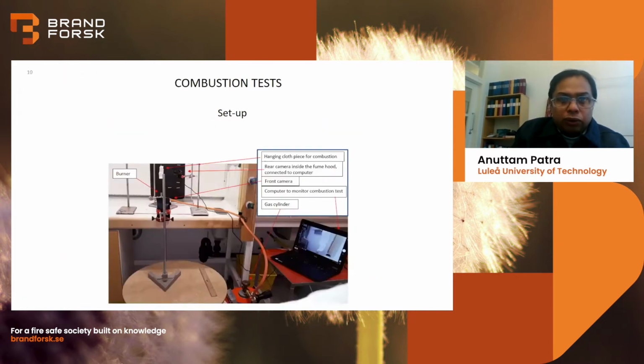Now I move to the simple combustion test setup that we used. We used a Bunsen burner, which is connected with a propane cylinder. The flame height was always 9 centimeters, which we controlled with the knobs. There is a certain distance between the flame tip and the cloth that is hung from the top. We used 2 cameras, one in the front and another inside the fume hood, which is connected to a computer. So during the experiment, we can also see the sample from the other side.